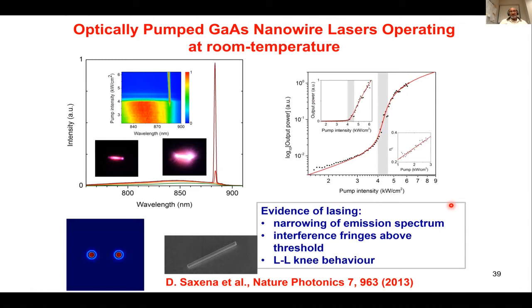To cut a long story short, based on this design, Dr. Jenny Jiang, who is now at Cambridge University as a postdoctoral fellow, has grown these gallium arsenide nanowires and transferred them onto a glass slide, and Drew Saxena has done the measurements. Below threshold, you see a very broad light emission like a light emitting diode. Above threshold, you see a sharp light emission like a laser, because it's acting like a Fabry-Perot cavity. You can also see beautiful interference fringes showing that coherent light is coming out. In fact, Drew Saxena has done simulations, and the simulations and experimentally measured coherent fringes match very well.